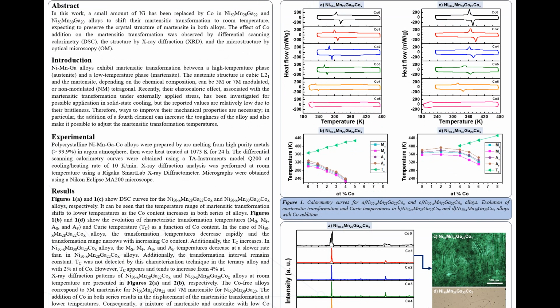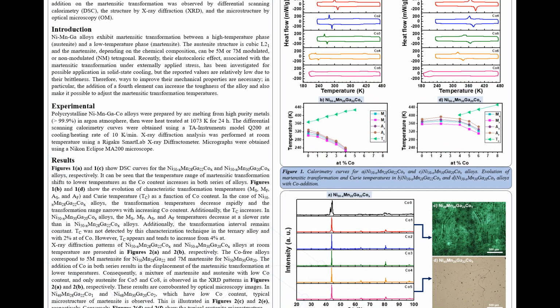Nickel-manganese-gallium alloys exhibit martensitic transformation between a high-temperature phase called austenite and a low-temperature phase called martensite. The austenite structure is cubic L21 and the martensite, depending on the chemical composition, can be 5M or 7M modulated or non-modulated tetragonal. Recently, their elastocaloric effect associated with the martensitic transformation under externally applied stress has been investigated for possible application in solid-state cooling, but the reported values are relatively low due to their brittleness. Therefore, ways to improve their mechanical properties are necessary. In particular, the addition of a fourth element can increase the toughness of the alloy and also make it possible to adjust the martensitic transformation temperature.